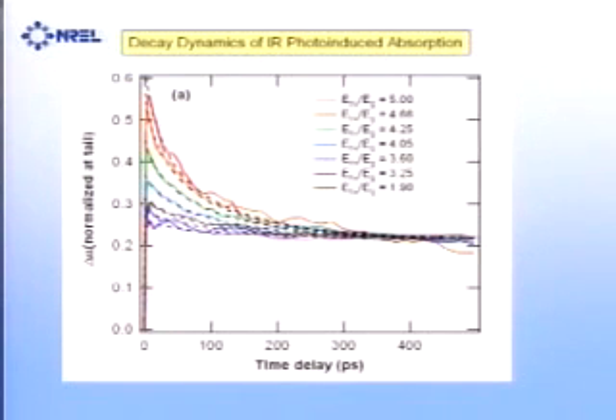This is a bleach. This is a photo-induced absorption in the mid-infrared, and we see growing in a fast component. And this is the signature of a biexciton or a triexciton, because the lifetime of a biexciton is much faster than a single exciton by orders of magnitude. The decay here is maybe 40 picoseconds. For a biexciton or a triexciton, it's about 20 picoseconds. And for a single exciton, it's nanoseconds. And we go through analysis based on the magnitude of the bleach, because that's proportional to the population, and the time scale of the decay.